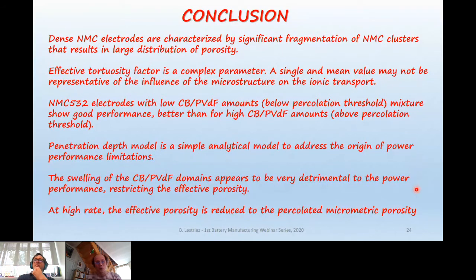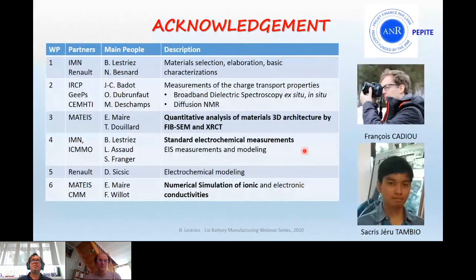We would like to stress the importance of the swelling of the CB-PVDF domains, which appears to be fairly detrimental to the power performance because they restrict the effective porosity, and at high rate this effective porosity appears to be reduced to the percolated micrometric porosity, which is influenced by the CB-PVDF swelling. I am really acknowledging all the people that have contributed to this project, in particular François and Sacris for their very nice work, and also the funding organization.